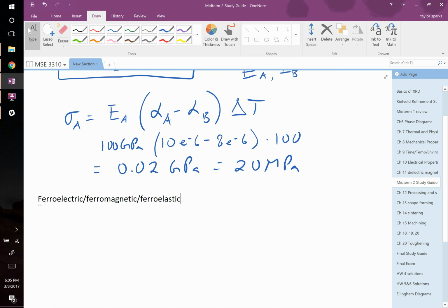You go below a certain temperature called the Curie temperature. There are actually some other names with ferromagnetics, but we're just going to call it Curie for now. The Curie temperature is where it spontaneously orders. Not the entire material all the way through, but some domain. Some number of unit cells spontaneously order in the same direction, right? For example, in barium titanate, it's about 120 degrees Celsius.